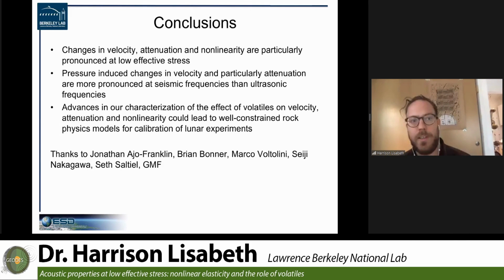So just some quick conclusions. The changes in velocity, attenuation, and nonlinearity are particularly pronounced at low effective stress, which is positive for looking at the lunar regolith. Pressure-induced changes in velocity, and particularly attenuation, are more pronounced at seismic frequencies than ultrasonic frequencies. So that is something to consider for designing experiments.